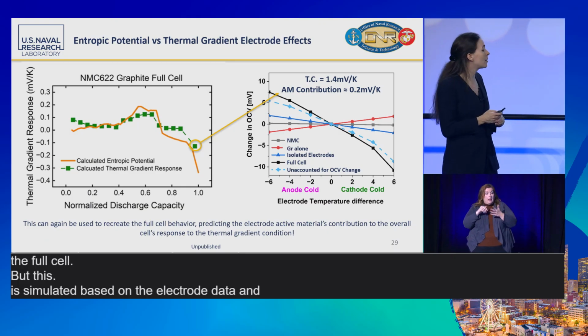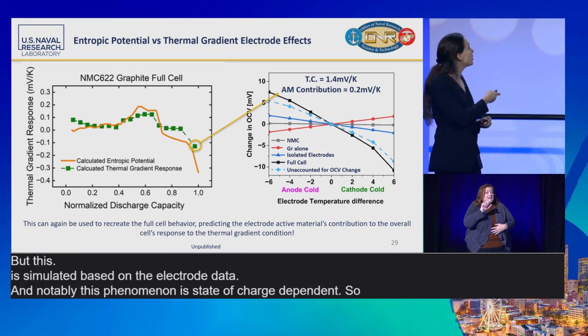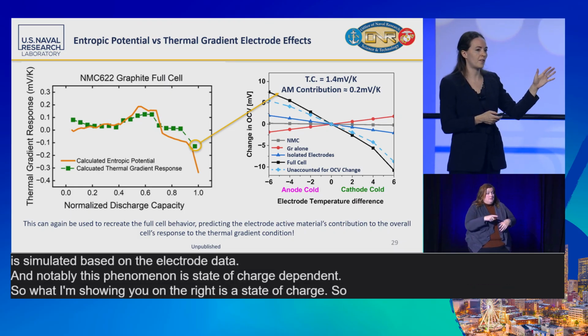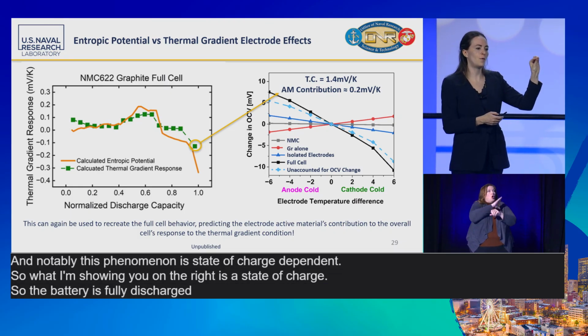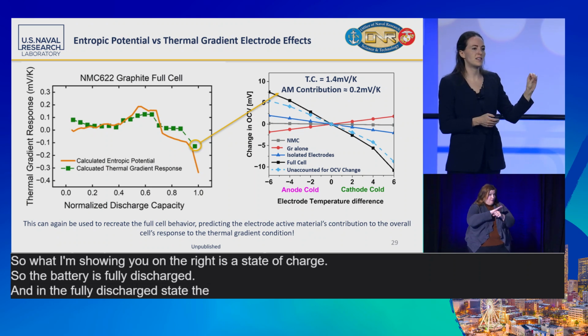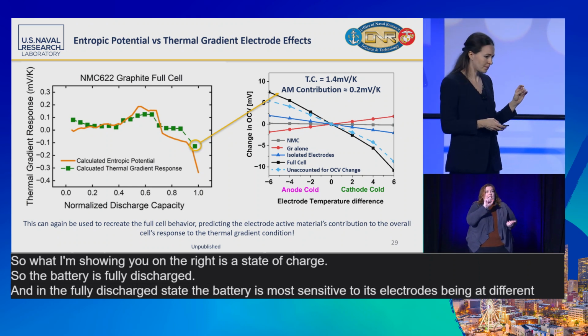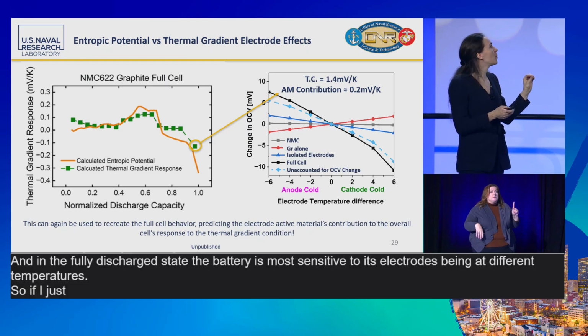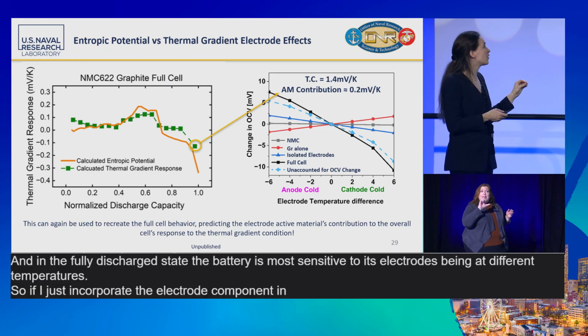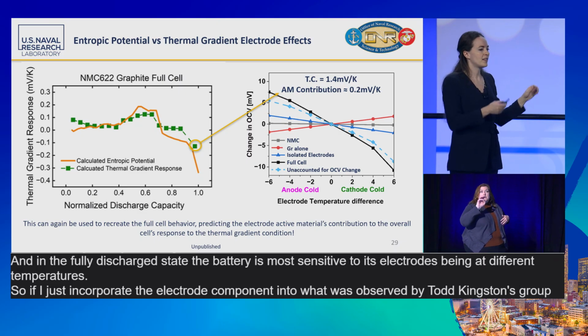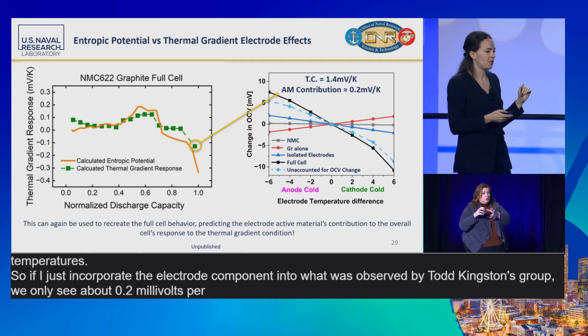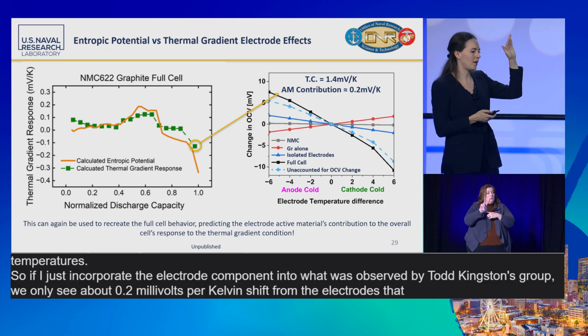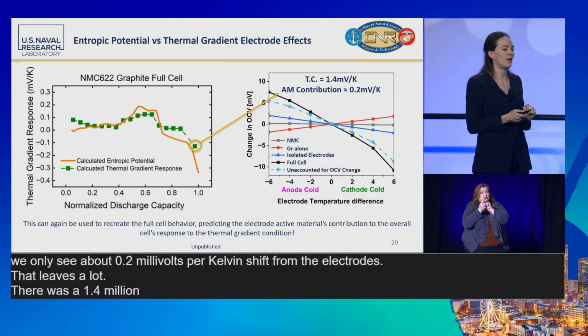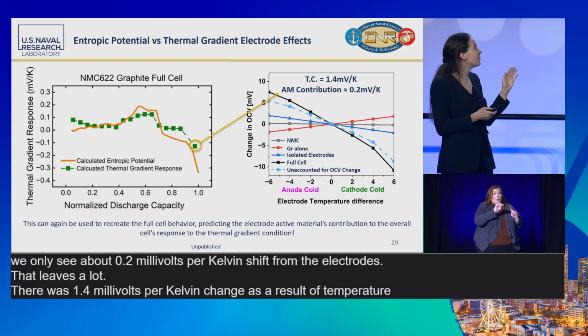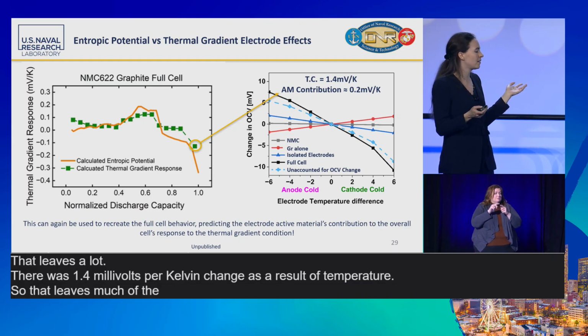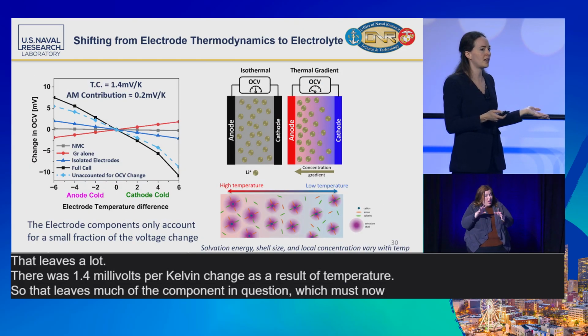And notably, this phenomenon is state of charge dependent. So what I'm showing you on the right is a state of charge, so the battery is fully discharged. And in the fully discharged state, the battery is most sensitive to its electrodes being at different temperatures. So if I just incorporate the electrode component into what was observed by Todd Kingston's group, we only see about 0.2 millivolts per Kelvin shift from the electrodes. That leaves a lot. There was a 1.4 millivolts per Kelvin change as a result of temperature. So that leaves much of the component in question, which must now be related to the electrolyte.